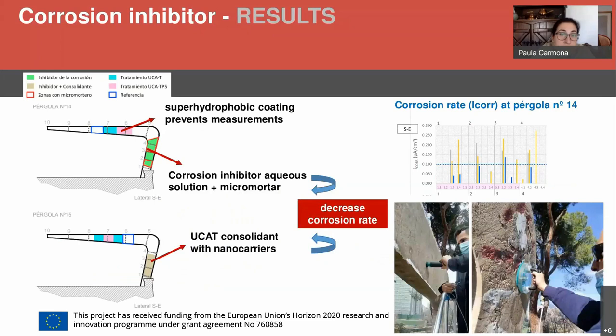As you can see here, these are the main results of the corrosion inhibitor. As we said before, we measured the resistivity and the corrosion potential, but I'm going to present the results of the corrosion rate, which are the most significant ones. And prior to the corrosion analysis, we identified 10 sections in the pergola. You can see here in the picture how the pergolas are. You can see here, from 1 to 10, the areas into which they were divided.